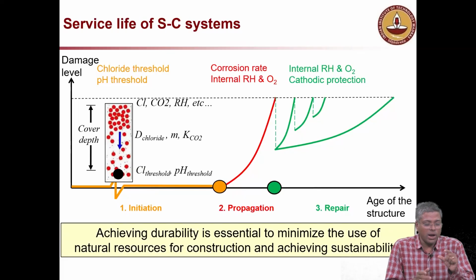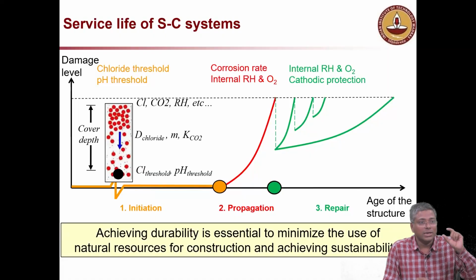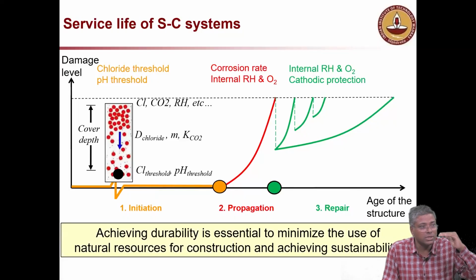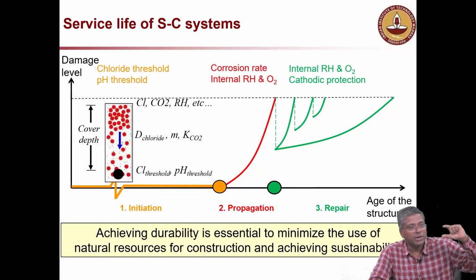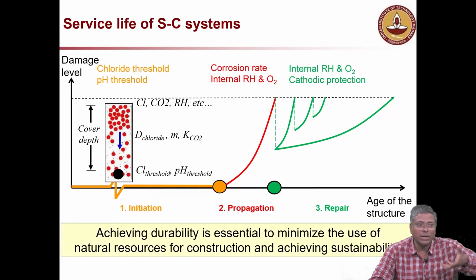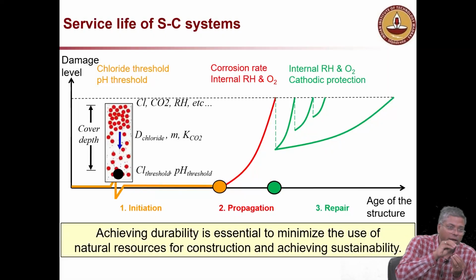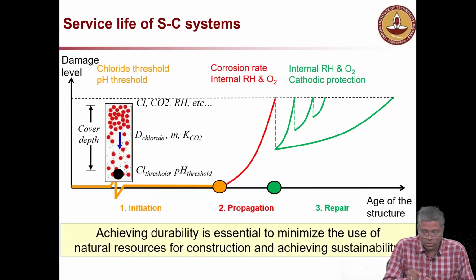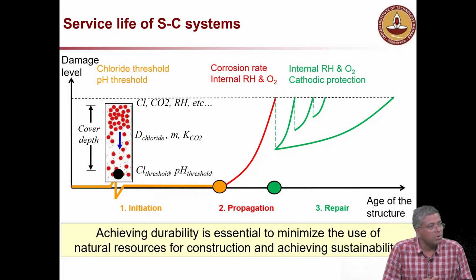Now, if I want that column to be free from corrosion for 50 years, I should make sure that the concrete used in the cover is so good that it takes 50 years for these chloride ions to travel that 40 millimeter distance, reach the steel, and build up on the steel surface. It's not that one chloride ion reaches the steel and it starts corroding. No, there is also something called the chloride threshold. It's written over there, which is the minimum amount of chloride required to initiate corrosion.